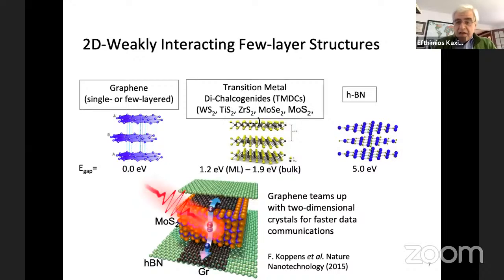And in fact, people have already been able to manufacture real devices. So here is a nice example from a few years ago by the group of Koppens and collaborators. So basically, they combined graphene, those are the green layers up here, with these semiconductors in the middle. So this is molybdenum disulfide, one of these materials, and they make a very interesting device where you shine light, and then the layers guide the electrons that are excited by the light only in very specific ways. So you can make a very interesting type of device for faster data communication. So it's not just hypothetical and interesting from the theoretical point of view. The materials and these combinations can actually make very useful devices.